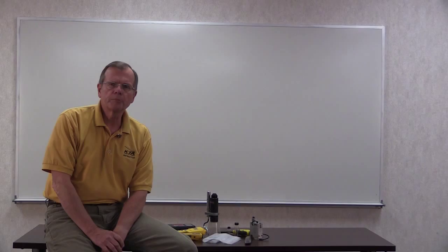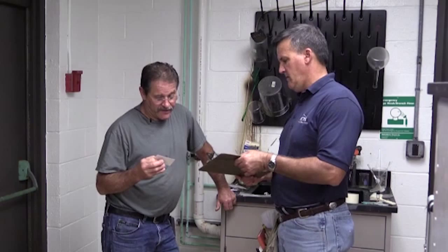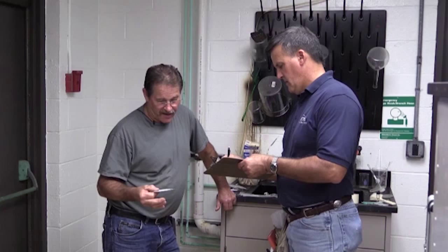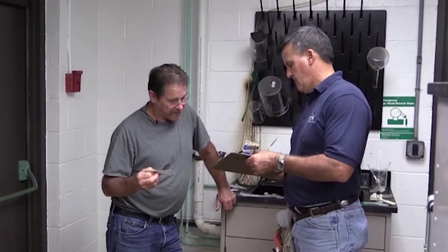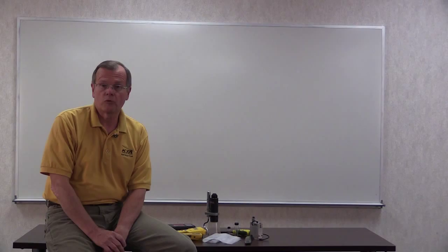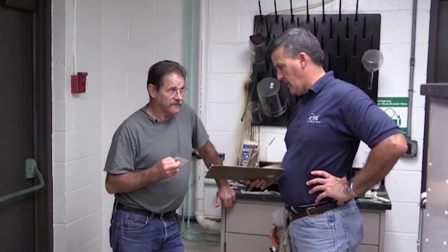Ask about surface preparation. It was prepared the day before. And what did you do to prepare it? Abraded it with a 60 grit open grain paper, swept it, and then mopped with a Simple Green multi-purpose mixture. Find out if moisture tests were performed. I had a fan blowing on it for the 24 hours and it was dry. But I didn't take a test to assure that it was dry. It was visually dry? Yes.